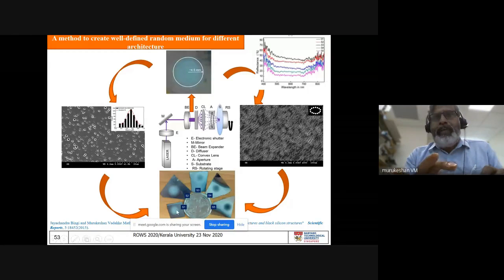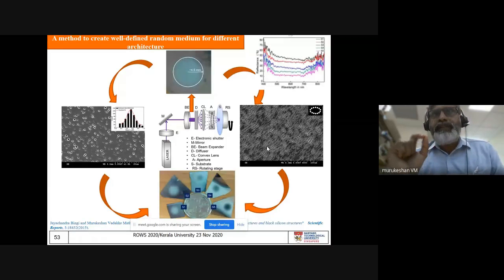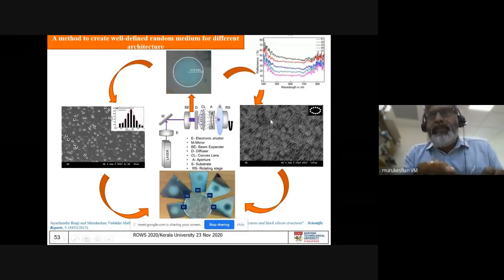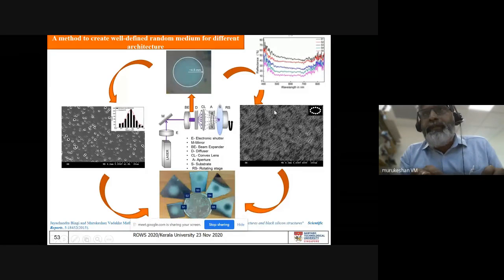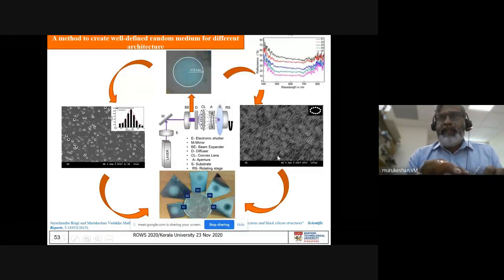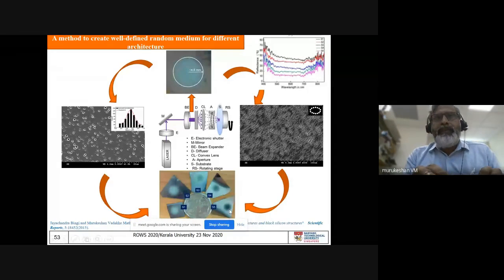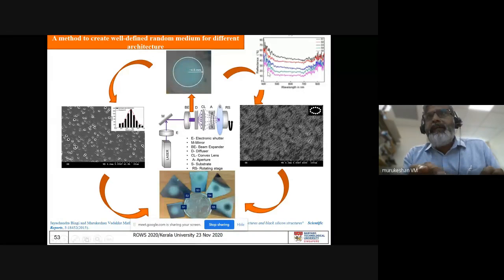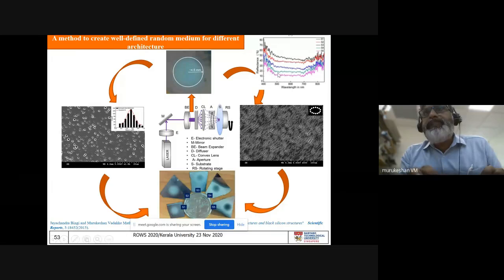From S1 to S4, these are the sample pieces where we have patterned these features. If you put this under a microscope, you can see these patterns. These patterns are, I will not say fully random, but quasi-random, because in a certain direction you can see it is periodic, but overall it is random as well. Depending upon the intent, the density of the pattern, we were able to make very, very dark silicon. And you can see that the reflectance for such patterns, when imprinted here, is reduced to less than 10%.